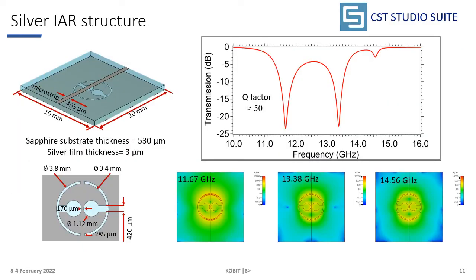The metallic inverse anapole resonator structure is obtained by patterning the geometry on the grounding plane of the broadband microstrip. Design and coupling studies with YIG thin film were performed using CST Studio Suite, by defining the Yttrium Iron Garnet as a gyrotropic material. The typical inverse anapole resonator pattern is modified to obtain two equally resonant modes by making circular gaps around the central conducting region. Even though the obtained quality factors are relatively small when compared to superconducting resonators, this type of resonator has an advantage in terms of filling factors of the microwave magnetic field through the magnetic medium.